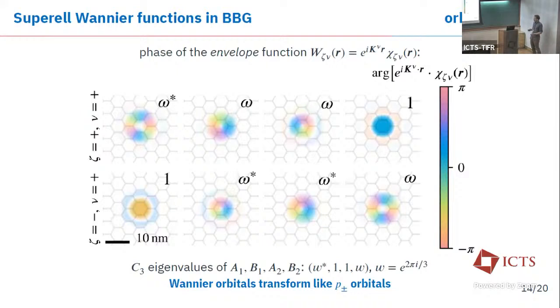So the last question to ask about those supercell Wannier functions and their transformation behavior is how they transform under symmetries, what kind of orbitals we actually wrote down. And we kind of have to disentangle the problem by taking our microscopic phase factors that stem from the valley degree of freedom and our macroscopic phase factors that are actually the phases of the Wannier functions. If we plot this in real space, again, this is the same plot as the red and blue one before for the absolute value, we see that we transform with zero phase windings in the dominant orbital, one phase winding in the non-dominant dimer orbital, and then a double phase winding in the opposite orbital.